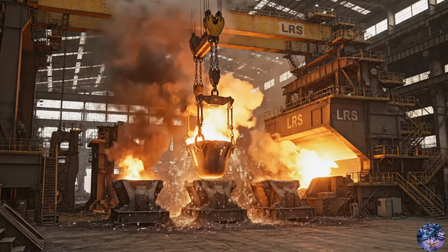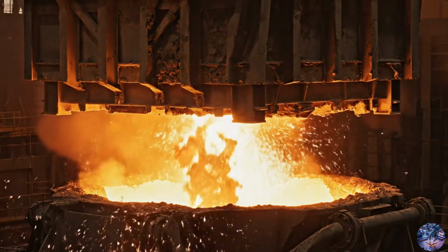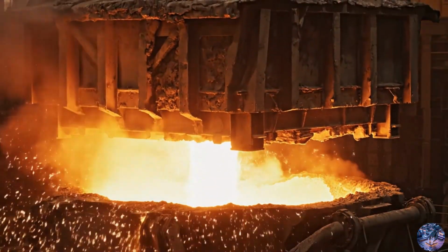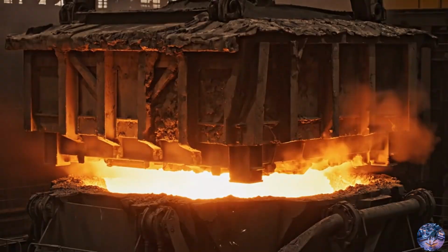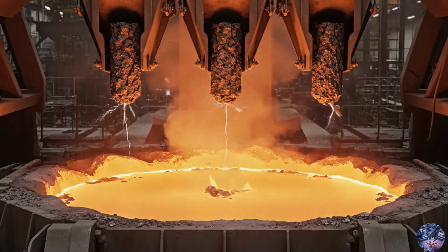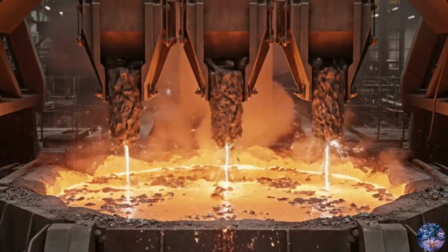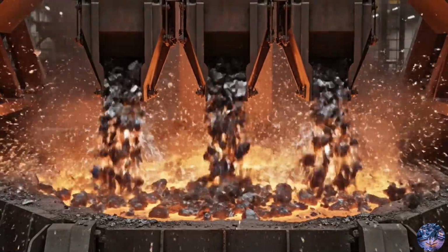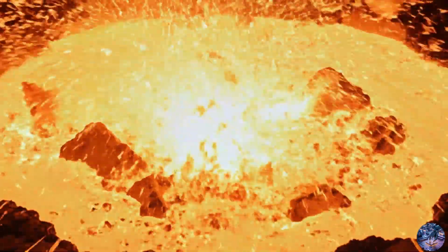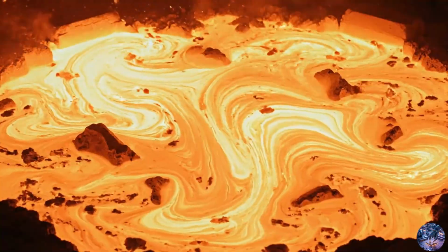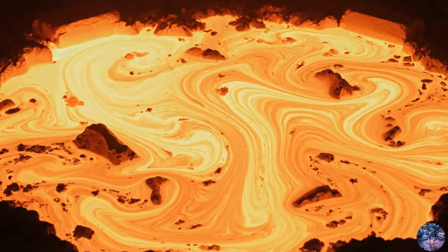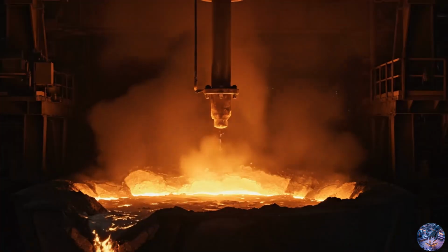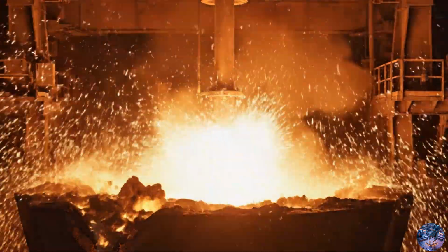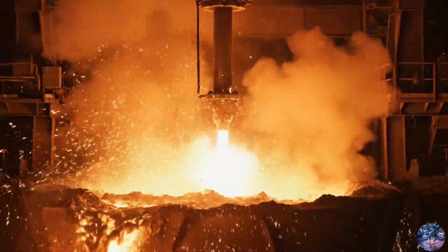In this state, the steel's carbon content is lowered until it reaches the perfect balance. The final layer of waste, or slag, is raked away by a powerful mechanical arm. This glowing residue is removed, leaving a mirror-like surface on the molten metal. From the bottom, argon gas is injected to stir the giant ladle. The steel boils gently, ensuring every inch of the 150-ton load is chemically identical.